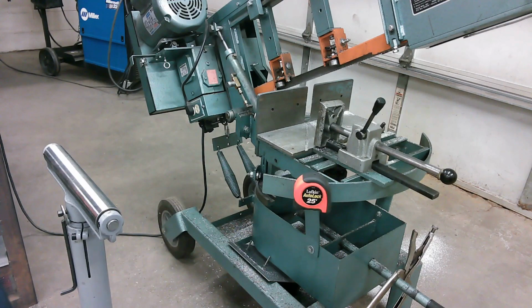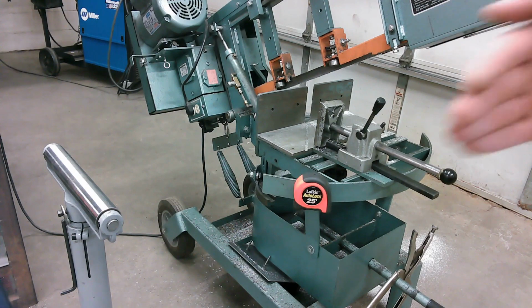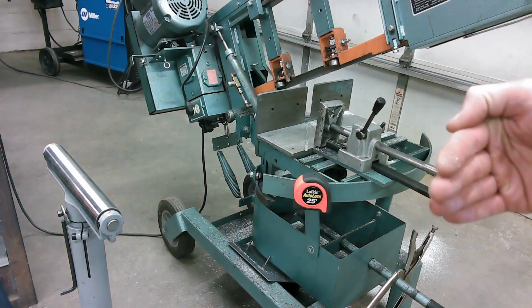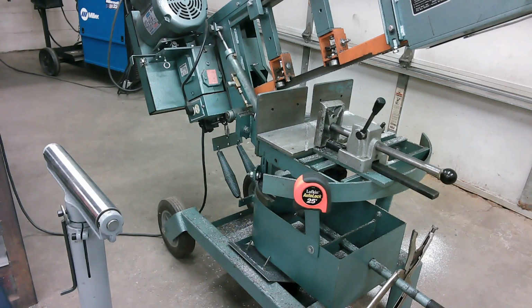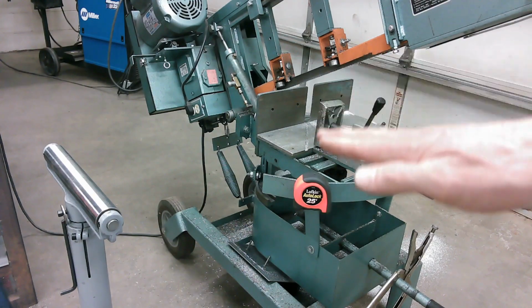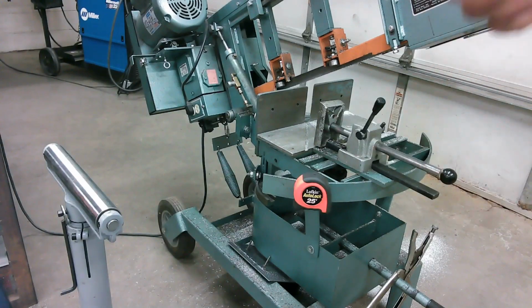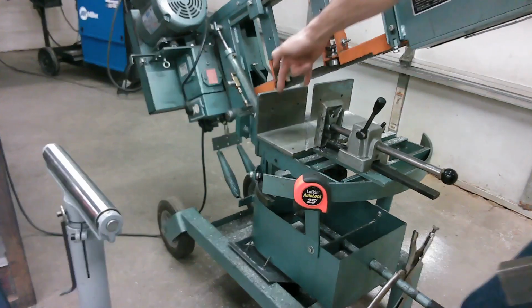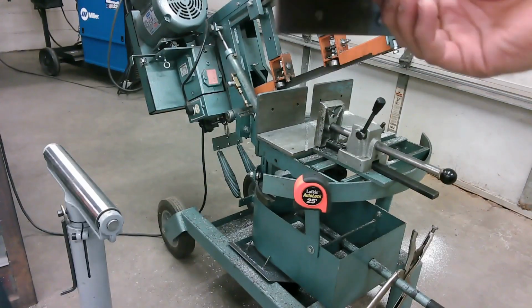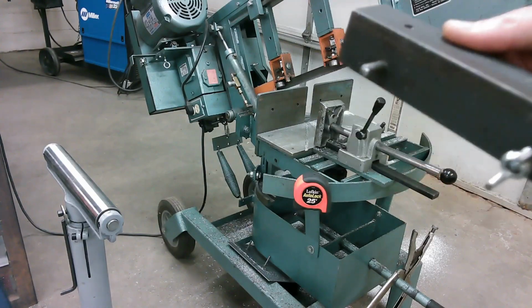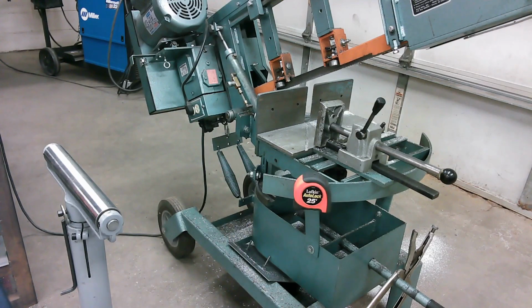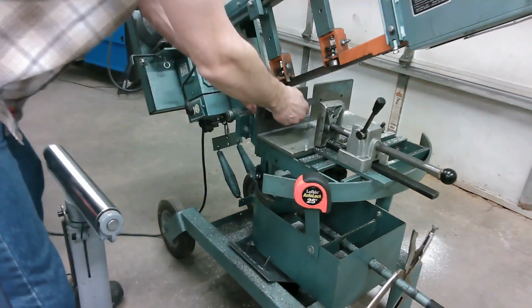All right, so we're out at our horizontal bandsaw. We have to make a slight modification to our saw. The plates aren't going to cut very well if we stand them up vertically because they're not flat. They just tend to sit there and vibrate, and we've got blade issues. If we lay them down flat, you guys know, trying to cut through a piece of 7-inch metal laid down flat, you don't have enough tooth pressure to get through that, and you're just going to sit there forever and dull your blade. So we found putting it at an angle is the best. There's a couple of holes in my fence right there, and we just simply took a piece of angle iron and welded some threaded rod. We use a couple of wing nuts on the back, and that attaches right to the fence. It's pretty easy, pretty quick.